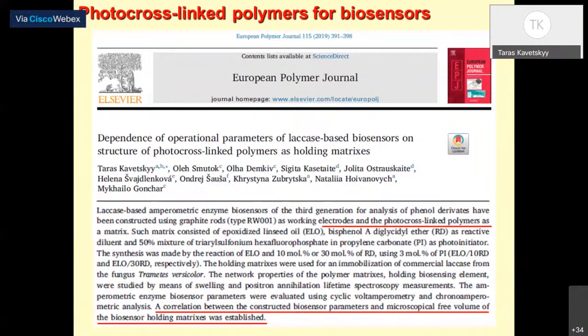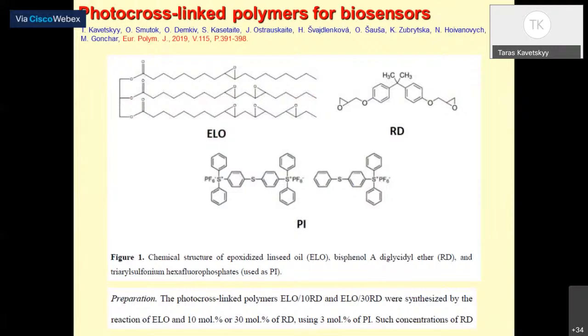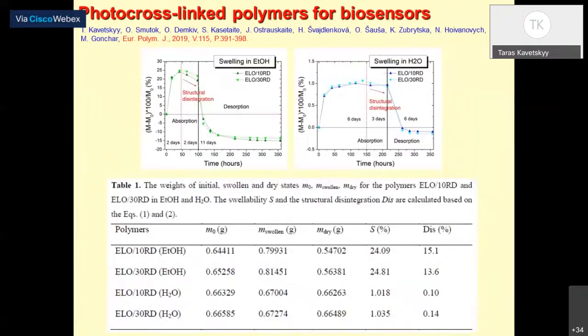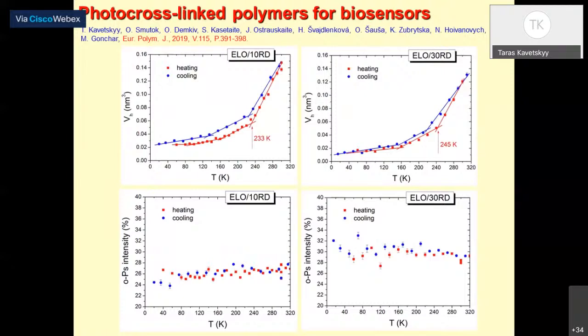Here are the chemicals of these photocuring polymers used. We use polymers with 10 molar percent of RD and 30 molar percent of RD, based on the epoxidized linseed oil. And here we study swelling results and found that this first polymer, ELO/10RD, has the lowest swellability and higher crosslink density. Also, this polymer shows the larger hysteresis between heating and cooling compared to ELO/30RD.